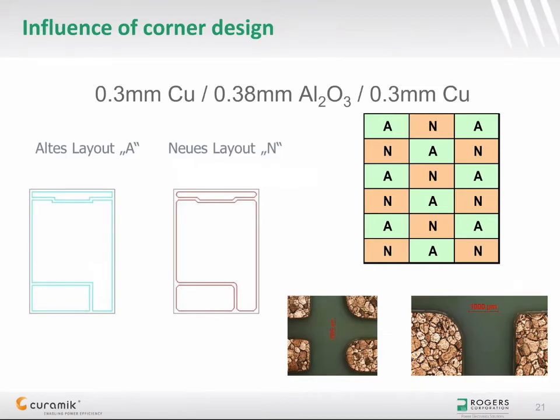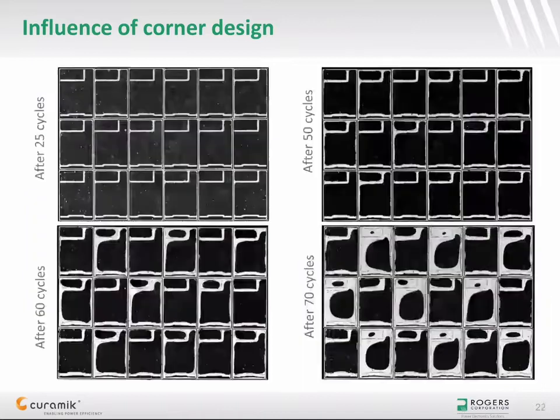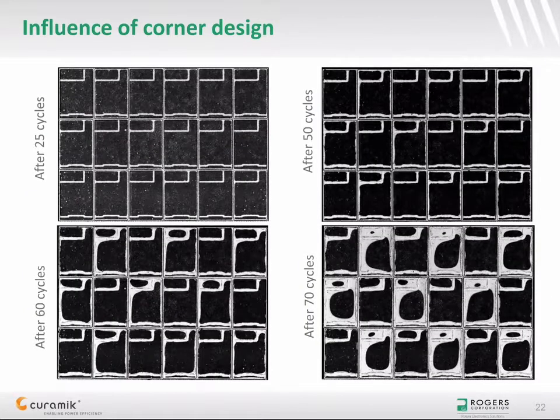Another way to increase reliability is again a design issue, and particularly the design of the corners of copper pads. The aim of a former study conducted at Rogers was to compare two identical layouts with sharp and rounded corners. The single units were arranged on a master card as shown on this slide. The acoustic images show that all parts, irrespective of their shape, have survived 50 cycles without any visible degradation. After 60 cycles, degradation is becoming visible for the substrate with rounded corners only. And after 70 cycles, this substrate is severely damaged, while degradation is starting for the substrate with sharp corners.